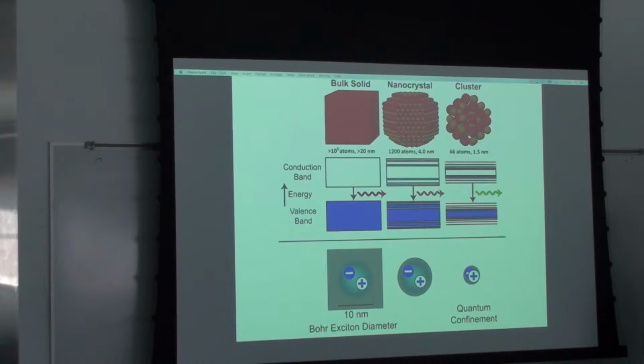And so we use that because if you put that wide band gap material on the surface, then the electron and the hole don't go into it. They stay in the core. That's called passivation. And so they basically are not impacted by anything that happens on the surface. And that's great because then they're brightly fluorescent all the time, which is a good thing for our applications.